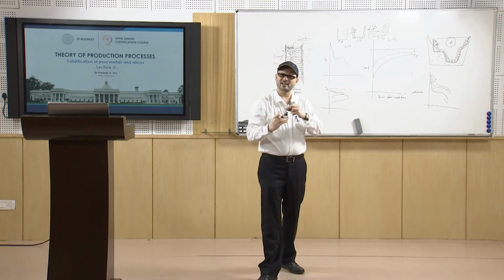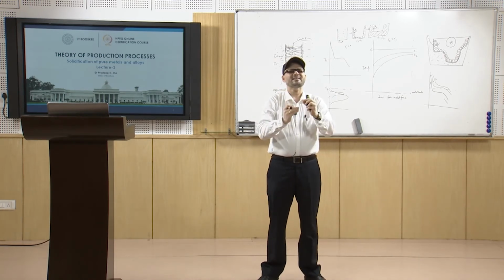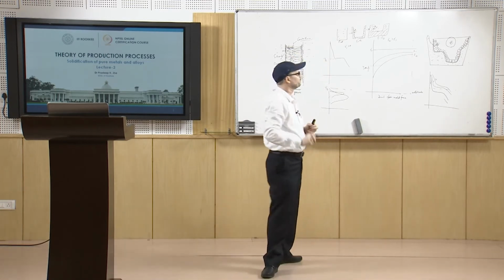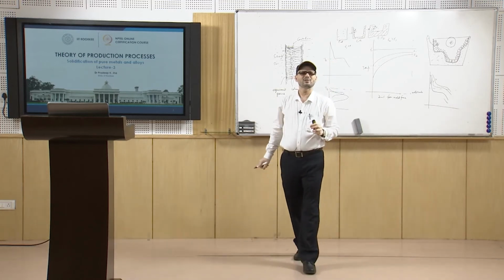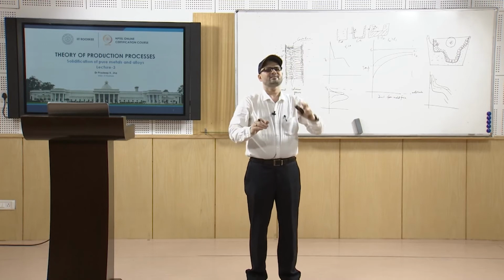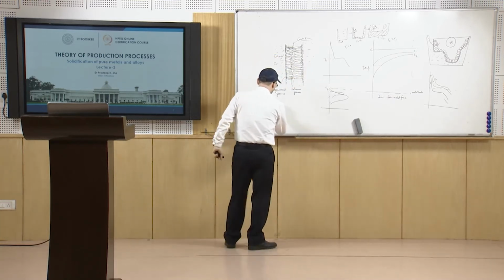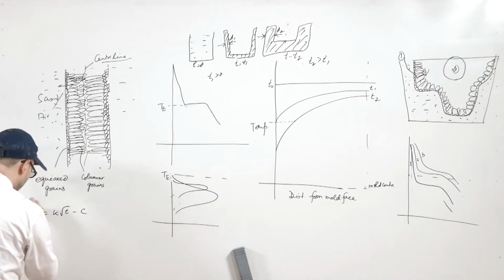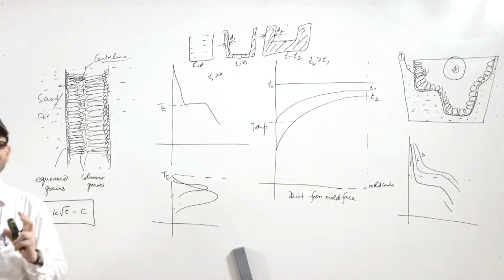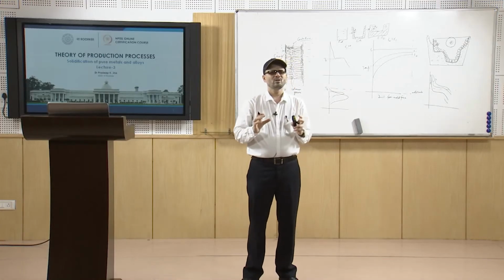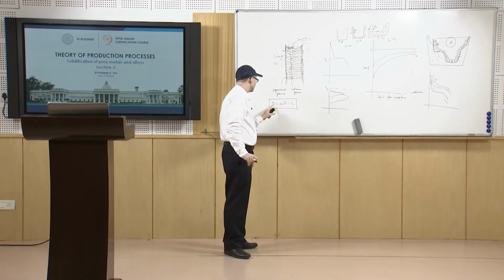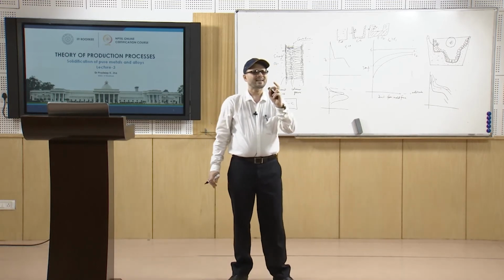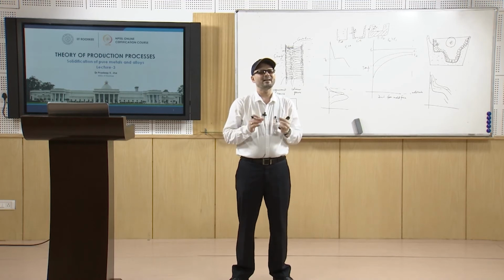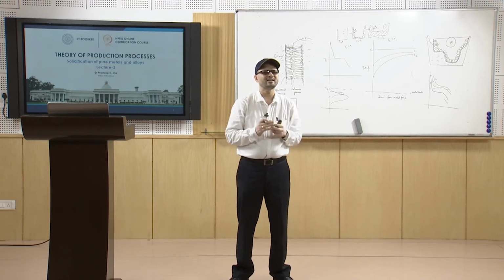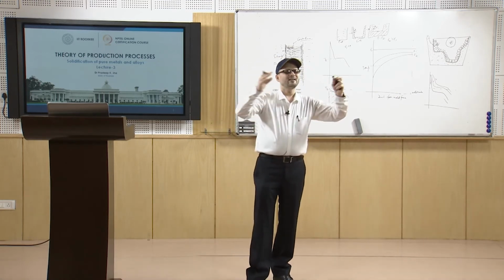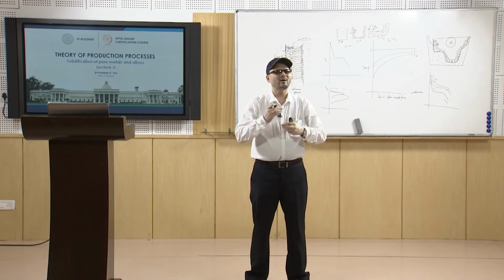So the skin which is formed, initially you will have a very thin skin formed, and slowly the thickness is basically increasing. So the thickness of this skin solidified will basically depend upon the time, and the formula is d equal to k root t minus C. This formula tells what will be the thickness of the cell formed at certain time. So, K and C are constants and d is the thickness of the skin. The magnitudes of K and C are determined by the size of the casting and how fast you are extracting the heat from the mold. So, that will depend upon the size of the casting, then the type of the mold, what kind of mold material is there.